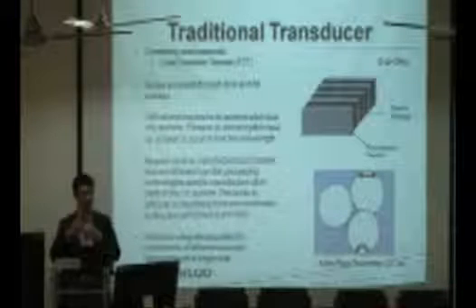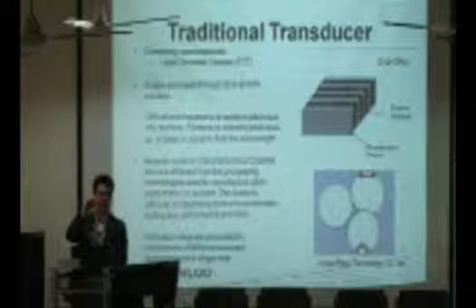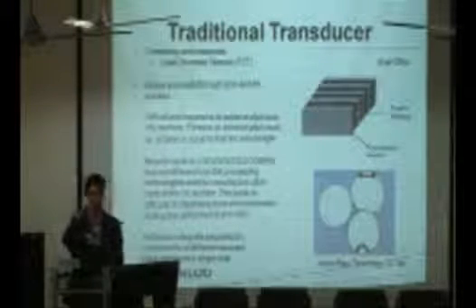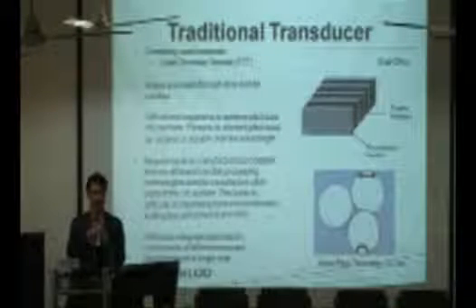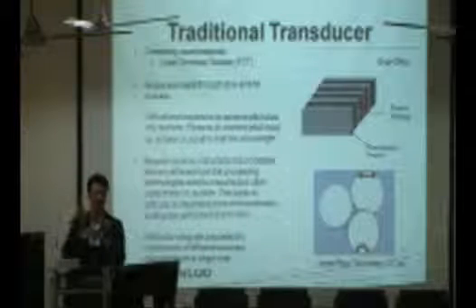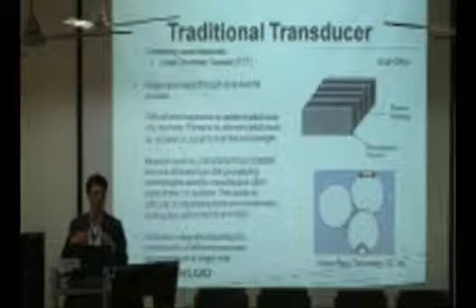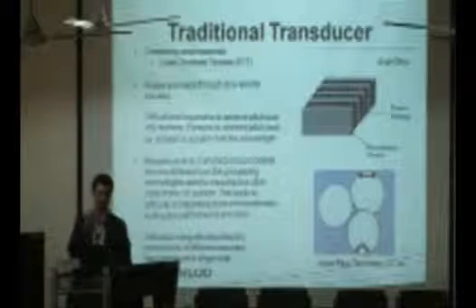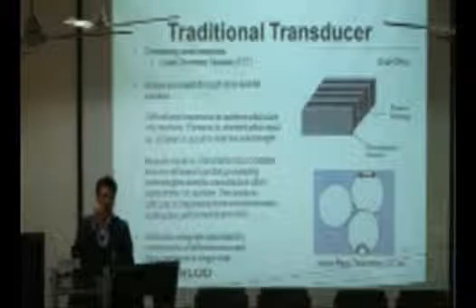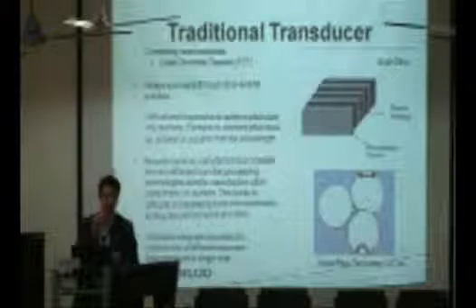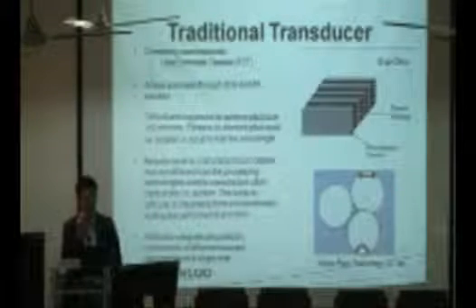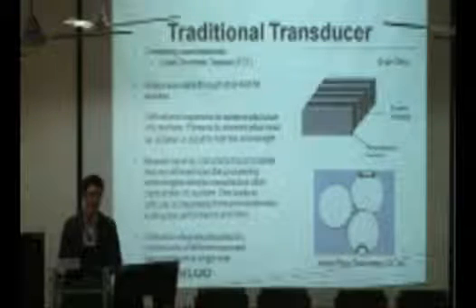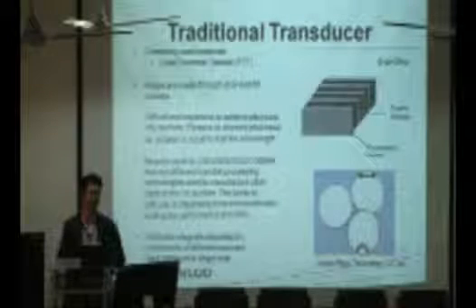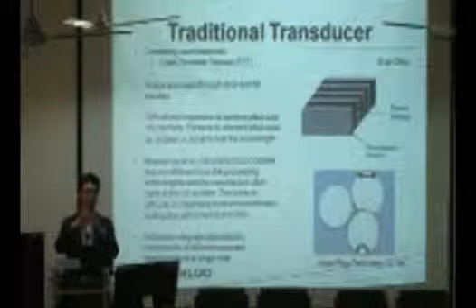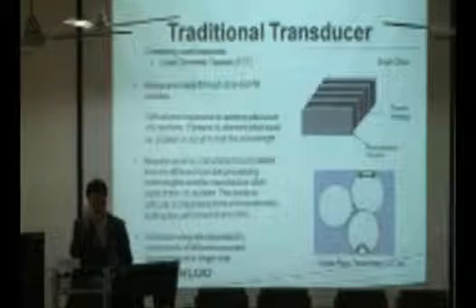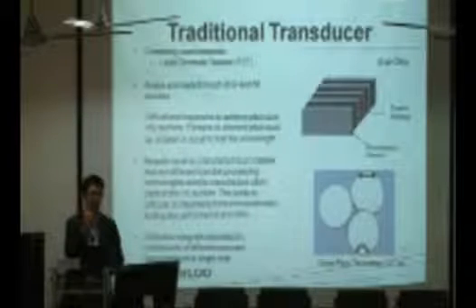So if we want to generate really high frequency from this small crystal, how do we change the frequency? Well, we need to cut the crystal down to a really small size, because a small crystal has a high resonant frequency, and a big crystal has a low resonant frequency. Now, at the level of 60 megahertz, we have to cut the crystal down to around micron dimensions. And each one of these conventional piezoelectric transducers is manually cut. There is no way to automate this. So if one goes to the hospital to perform ultrasound imaging, if you break apart that machine and look at that piezoelectric transducer, that was cut manually.